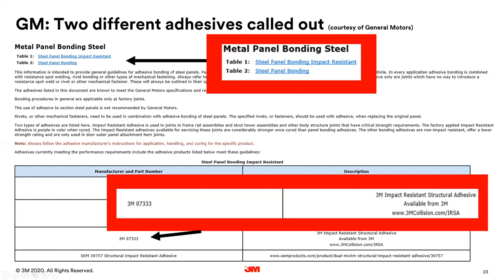So they say the other bonding adhesives are non-impact resistant, offer a low strength rating, and are only used for door outer panel hem joints. So the rule of thumb for GM, but again, always look in the procedure, things can change, but the rule of thumb is if it's a door skin, it's 8116. If it's any other bonding operation where they call out an adhesive, it's going to be the 7333, okay? So that's their general rule of thumb, but always look at the procedure to make sure.